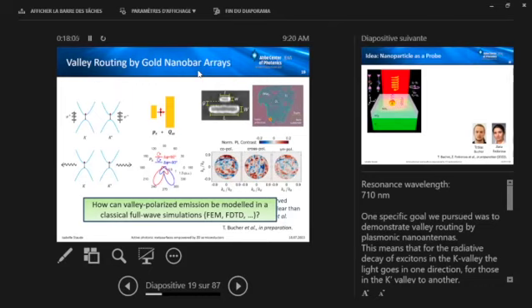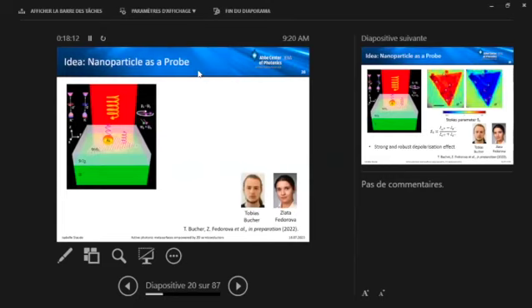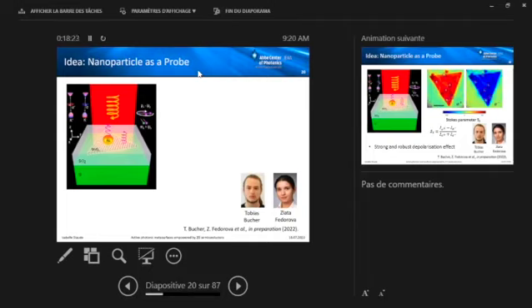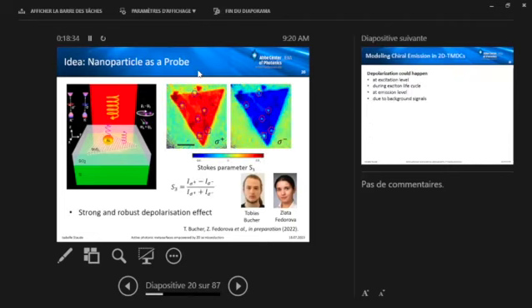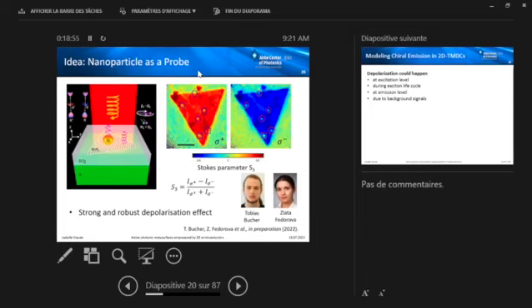So, our question was now, how can we more reliably model valley polarization in a classical full wave simulation. And for this, we went back to a much more simple system, just a gold nanoparticle on an MOS2 monolayer separated by a little dielectric spacer layer. And we were then doing these quite challenging experiments here at 4 Kelvin, and we're pumping this with circularly polarized light and looking at the photoluminescence emission. And basically, this is what we find. Here we have a monolayer flake for sigma plus and sigma minus excitation and at the points of the nanoparticles, which are in the circles here, we find a strong and robust depolarization effect, which really survives for many different samples, many different excitation detection experiments and so on.